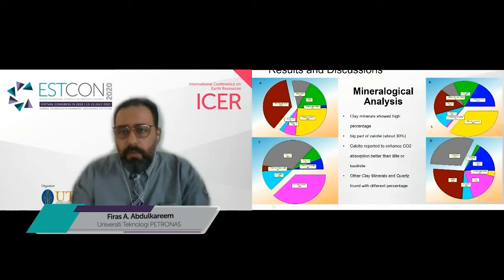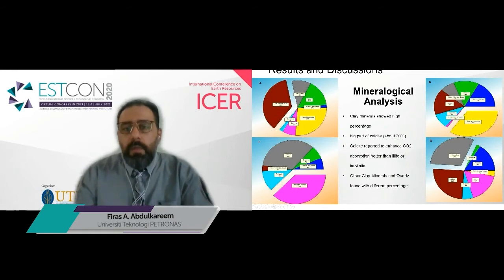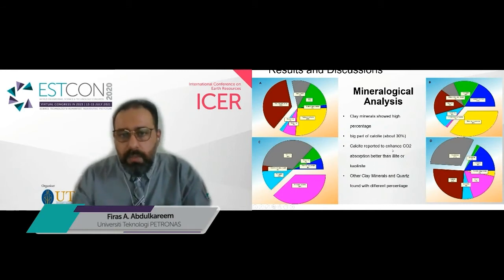And as we can see from the mineralogical analysis, calcite in some of the samples shows a high percentage compared to the other clay minerals. On the other side, some feldspar and quartz show a feasible amount as well. On CO2 absorption in particular, calcite is reported to enhance CO2 absorption better than illite and kaolinite. On the other hand, other minerals like quartz and feldspar have always had a negative proportional effect on the absorption